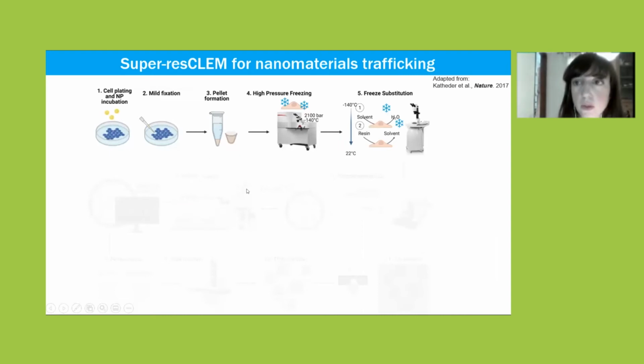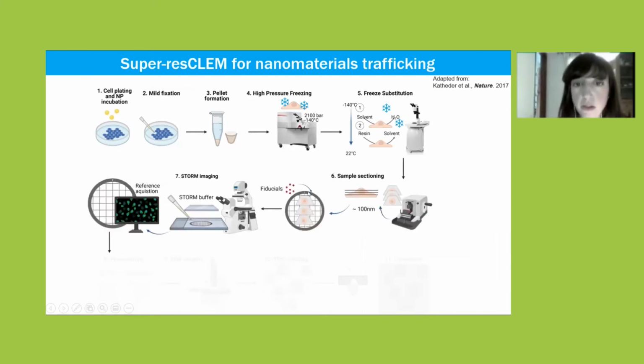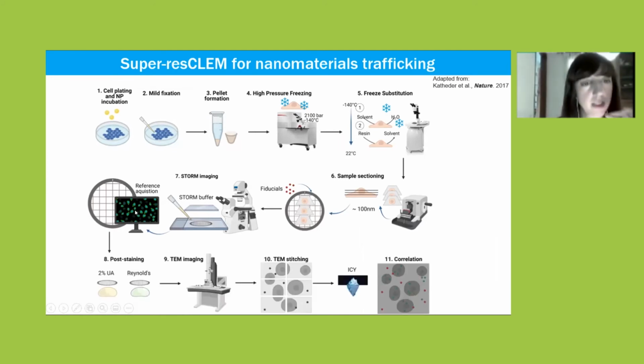So this is the protocol that Theodora has been using. So we incubate the cells with the nanoparticles. We do a mild fixation. We get the pellet, no? Then we do high pressure freezing, freeze substitution, then the sectioning. We add the fiducials, the STORM buffer. Then we do the STORM acquisition. And then we retrieve the grid from the chamber. We do the staining and then the TEM imaging, the TEM stitching, and then using ICY software, we get the correlation.